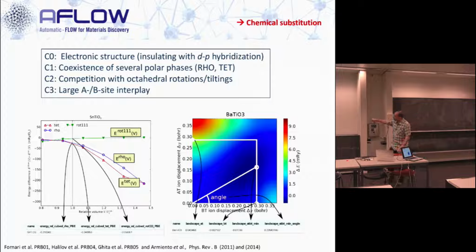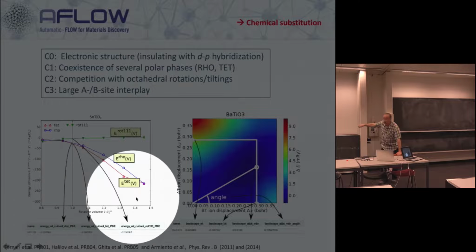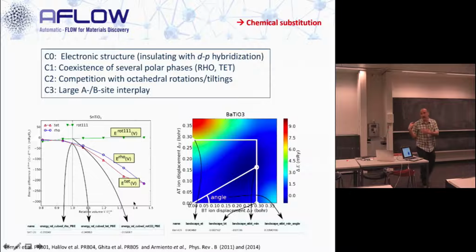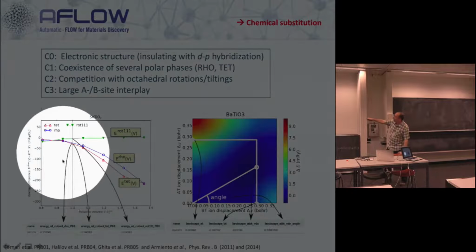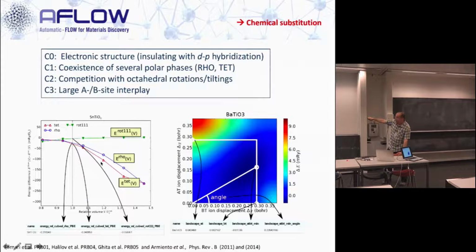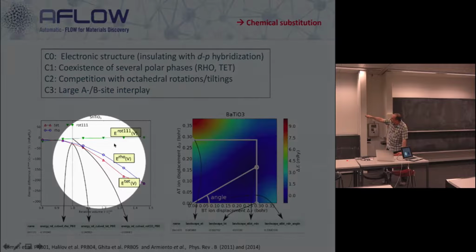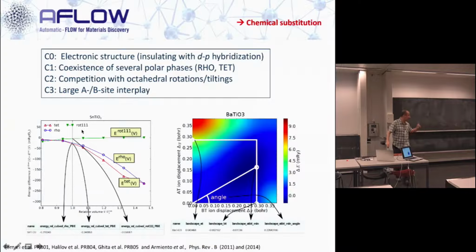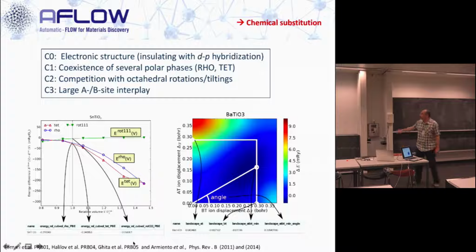So our calculations were done this way, where we scan across different volumes. And the reason is that the physics of the piezoelectrics is very sensitive to volume. Then we look at the energetics of rhombohedral, tetragonal, and rotational distortion. And we plot the curve. We set the equilibrium volume, the theoretical equilibrium volume. This was a decision taken a posteriori after I had done all the calculations. And we stick those in our database. Okay? This takes care of criterion 2 and criterion 1.